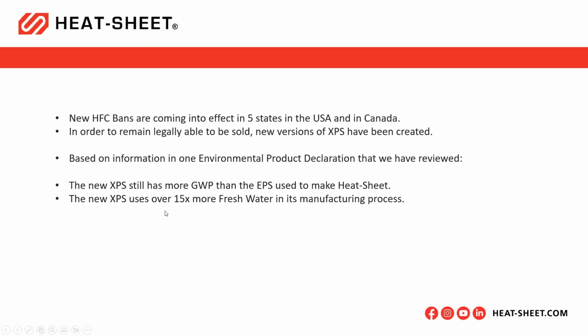And one other thing, the new XPS has gone through different iterations. Regulations came out because of the high global warming potential, so they had to change their manufacturing processes. It turns out that this new manufacturing process does have somewhat lower GWP, but it tends to use 15 times more fresh water in its manufacturing process for some reason. That's an incredible amount of fresh water to be used. So it's another reason to consider using EPS: the conservation of fresh water.